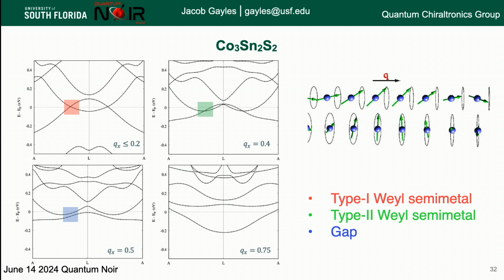And so at very low values, it behaves like a Weyl material, what's called a Weyl semi-metal. As we start increasing the spin spiral, this is also increasing the temperature, we get a phase transition to a type 2 Weyl semi-metal. And as we increase it further, we gap it completely because there's a magnetic field there that gaps the electron states there. And then we also get these flat bands, which are known, but also very interesting.